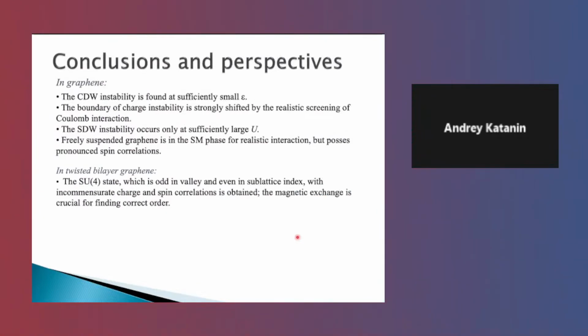So here is the conclusion of my talk. We find the charge density wave instability in graphene at sufficiently small, unphysically small permittivity epsilon. The boundary of charge instability is strongly shifted by realistic screening of Coulomb interaction. The spin density wave instability occurs also at unphysically large local interaction. Therefore, freely suspended graphene is in the semi-metal phase, but possesses strong spin correlations. And in twisted bilayer graphene, we find a kind of SU4 state, odd in valley and even in sublattice index, with incommensurate charge and spin correlations.